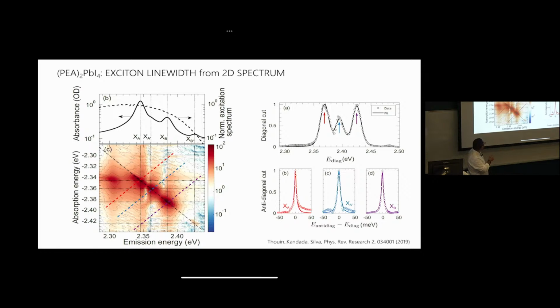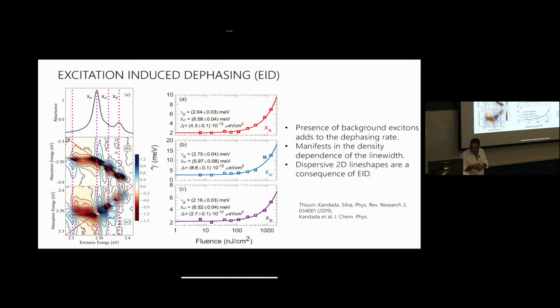We also see features here which are biexcitons. We can measure biexcitons. Biexciton binding energies are different for XA and XB. I'm not going to talk about this, but that's something else that is a consequence of the lattice. But we see this spectrum, and we can analyze the line shape to separate homogeneous and inhomogeneous contributions through a line shape analysis. Won't get into the details, but that's the exercise here. So you do that, and you can measure dephasing, and that dephasing is going to depend on two things.